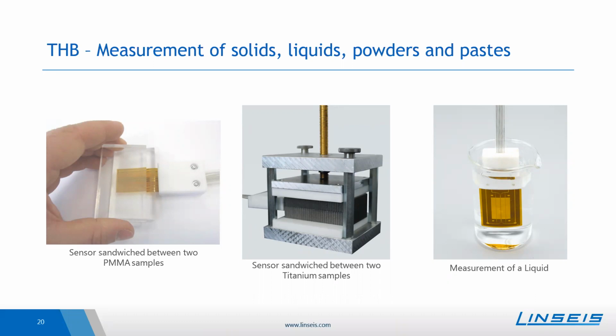But it is in general also possible to measure slightly rough surfaces. If the surface is too rough or too scratchy, one can, for example, also put in a very thin layer of a copper paste or another thermal paste to smoothen out the surface. Typically, a very thin layer of such a paste does not influence the measurement itself too strongly, so that there's not too strong deviation of results due to the sample preparation.